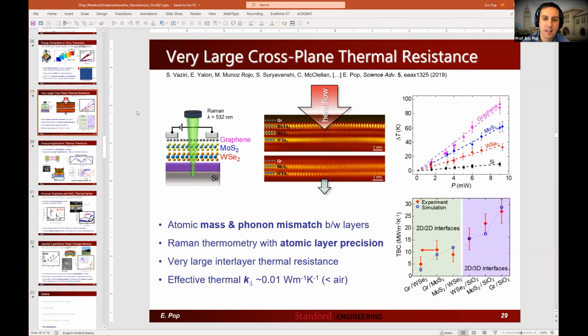But it turns out that if you rotationally misalign these materials, they don't stack exactly with the same layer spacing. So rotational misalignment changes the layer spacing, which also changes the thermal transport. And in some cases, if the spacing is a little bit larger, it'll lead to lower thermal conductivity. If they're closer together, with smaller van der Waals gaps, you have higher thermal conductivity. I don't think you can make the thermal conductivity very high like this. I could be wrong,